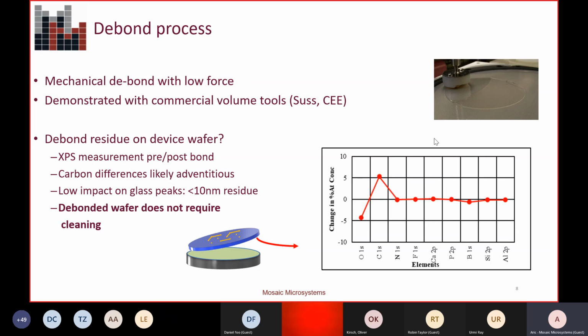But what we're seeing, and what I'm showing here in the plot in the bottom right is the difference between the bonded layer and the debonded layer. And basically, the only difference you're seeing is in the carbon and the oxygen. The carbon, we believe, is adventitious carbon, and then the oxygen could be related to some of the processing. Oxygen gets a little bit depleted on the surface. But by and large, you're not seeing any contamination whatsoever from these other components. And nothing was done in between the debond and the XPS measurement. So there wasn't any cleaning or polishing. So it's a very, very clean bond surface that really allows good integration for flipping the wafer and then doing backside metallization, for example.